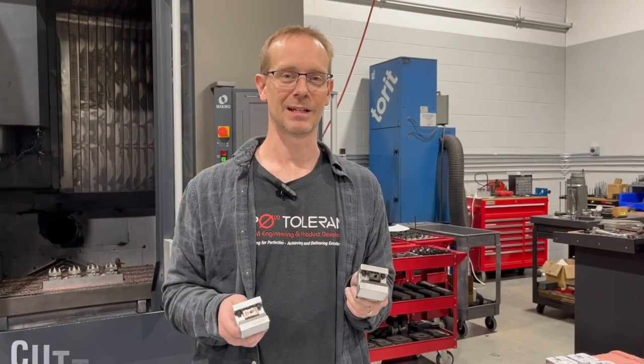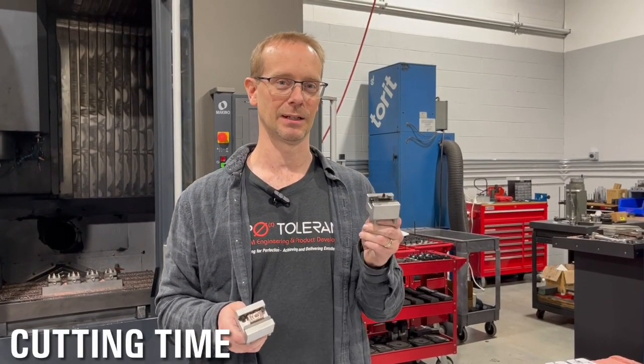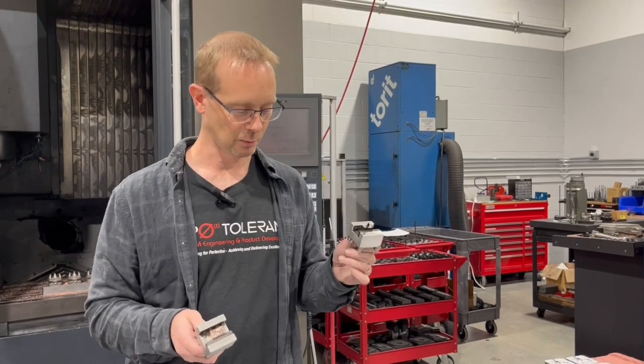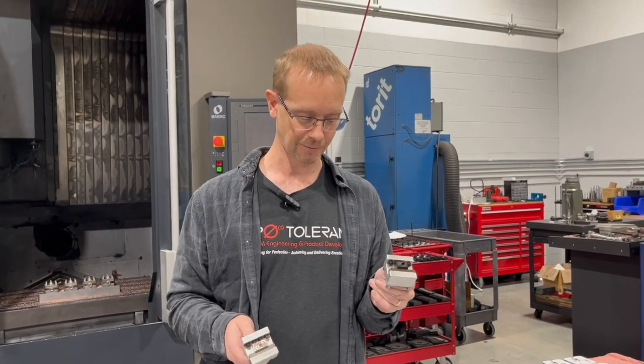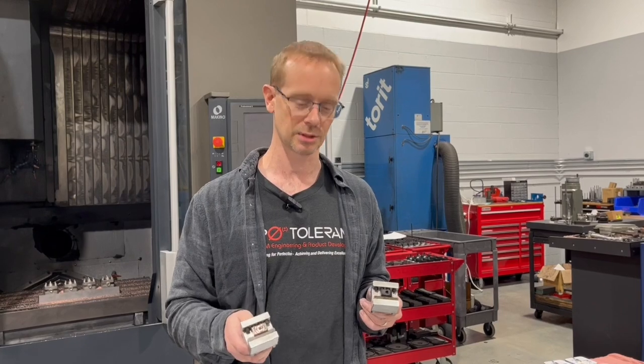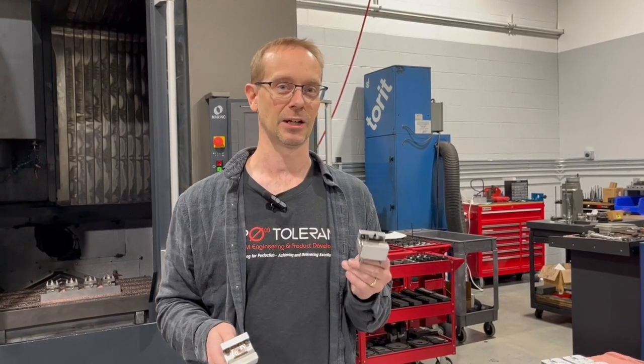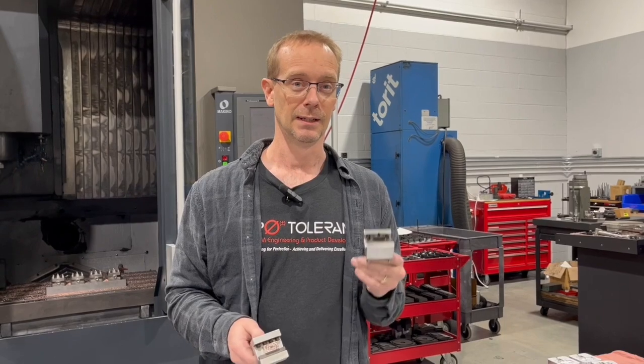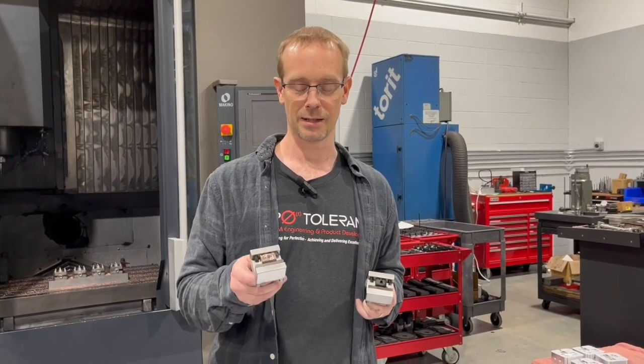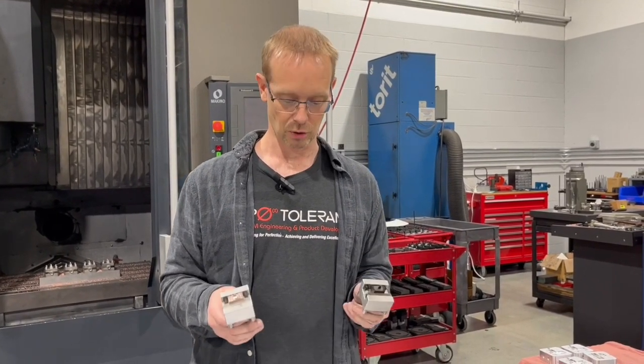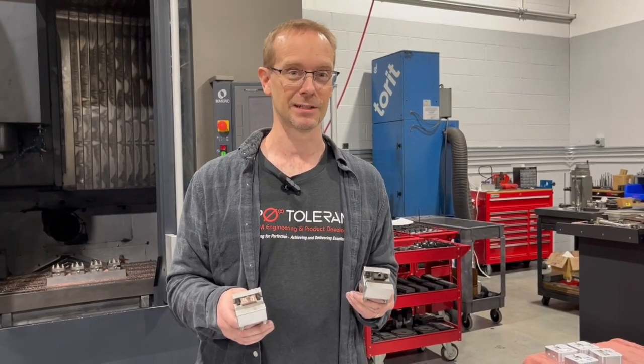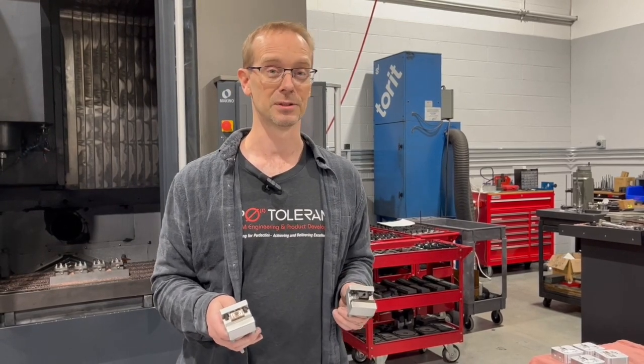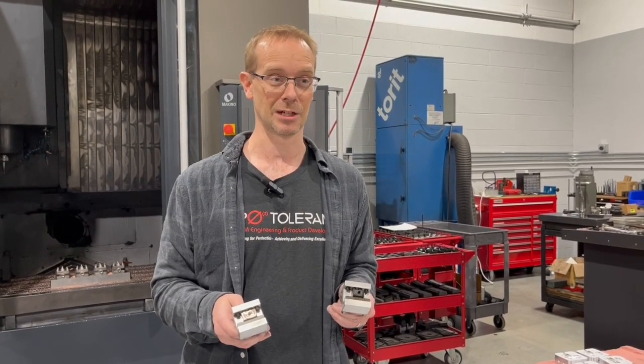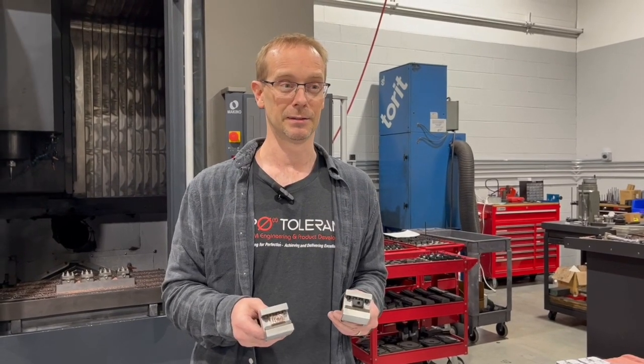I want to cover the time difference it takes between cutting graphite versus copper. What we found is the copper took 44 minutes to cut 2 electrodes, and in 14 minutes we cut 3 graphite electrodes. And this is POCO 3 and copper tungsten. So that's a big difference in timing to machine, especially if you're cutting a lot of electrodes. So that's a huge gap in time. And we're gonna compare benefits and all that.